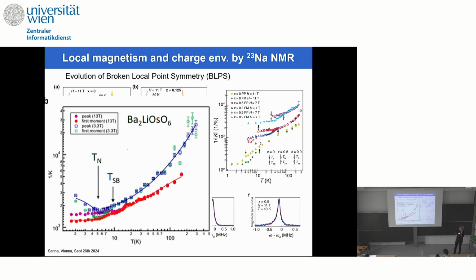Now, just to tell you that we have preliminary data also for the lithium material, and here, if you look at these curves, these are at 13 Tesla, and we have a splitting between this curve and this curve. We have a splitting also here, anticipating the magnetic transition. Actually, we need to improve our fitting, because with the lithium, the quadrupole moment is smaller than sodium, so the effects are typically lower.